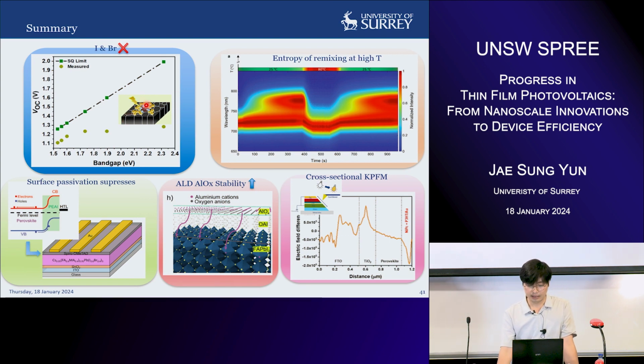And this halide segregation, phase segregation, can be suppressed under 80 degrees. There are also many ways to passivate the surface to suppress the halide segregation, and aluminum oxide can be used to improve stability. And we have very good cross-sectional KPFM techniques to observe what happens at the interface. So you can also study degradation mechanisms at the interface using cross-sectional KPFM.